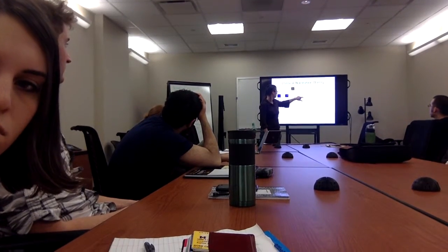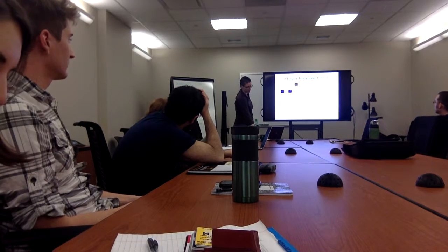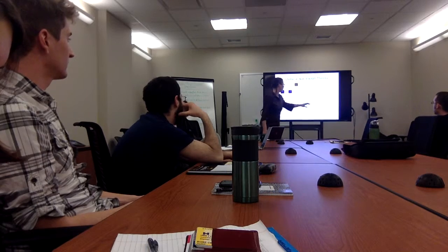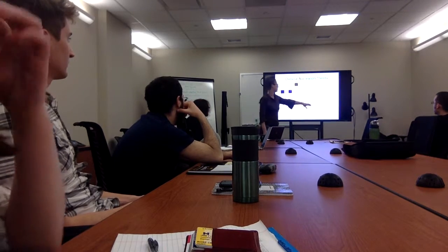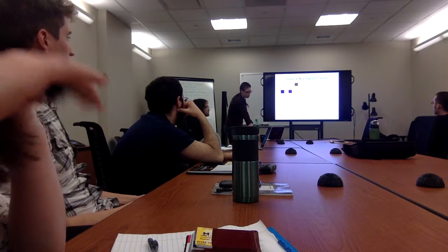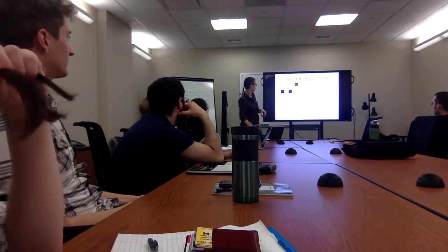So it's just saying that I is proportional to the probability of forming the crystal, and also proportional to that, and the proportionality is captured in this kinetic prefactor. This is also part of classic nucleation theory, where that prefactor is not always, but often written as a product of three different terms. One is the density in the fluid. So how likely are there to be particles there able to attach?